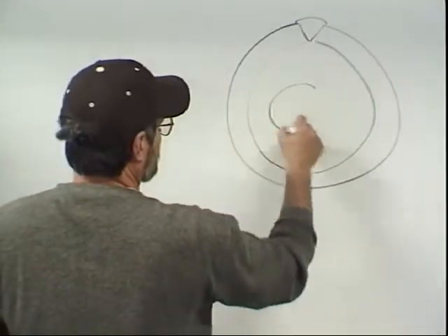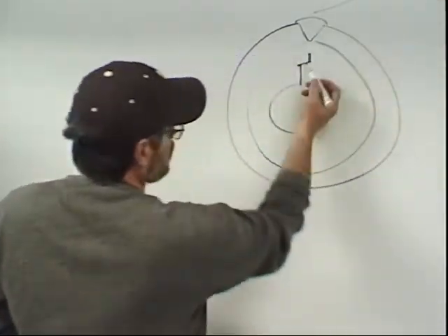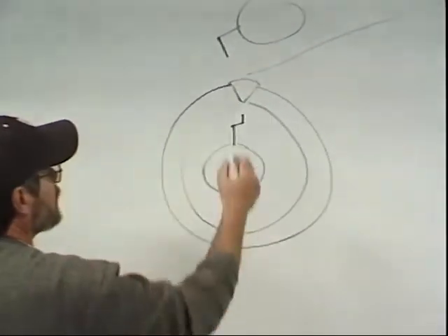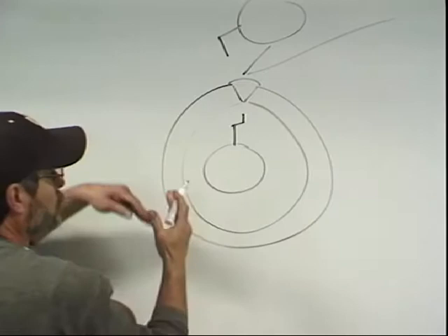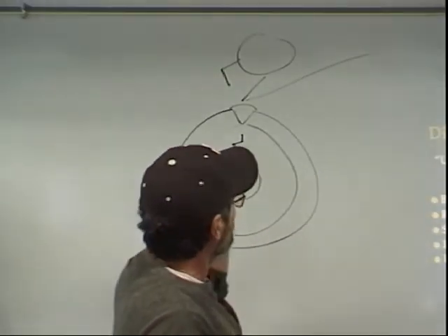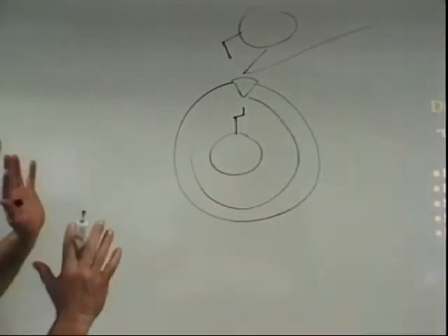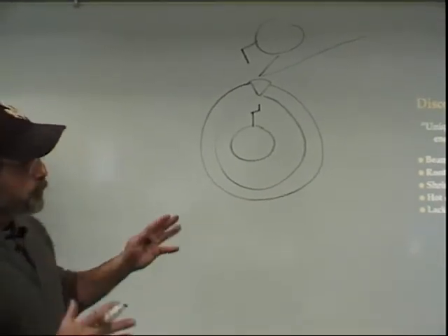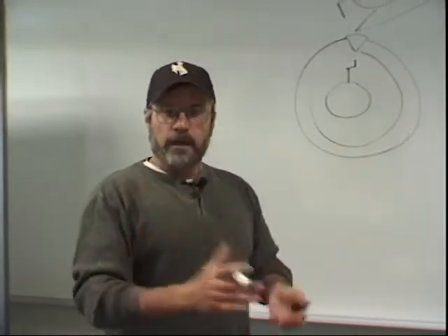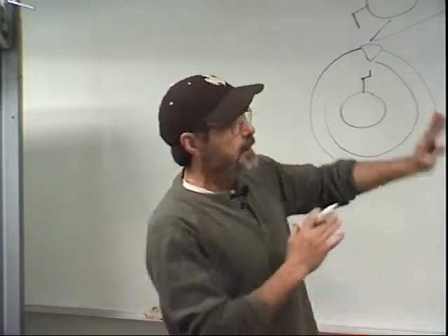And what they did was they ran a machine up the inside of this material, and it was welding from this side. They ran another machine on top, welding from this side. So they made a weld here from both sides using automatic TIG, and I'm almost certain it was TIG, and they ran it down 20-foot lengths or whatever and sealed it off. And then when this material was done, they pressure tested it. They capped both ends and they pumped it up with working pressure plus 10% or whatever, and it held just fine. So great, pass test, ship it out.